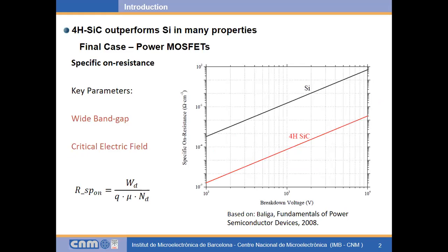Well, our final use case are power MOSFETs, silicon carbide power MOSFETs. In this way, silicon carbide outperforms silicon in most of the main properties. Here we have specific on-resistance with respect to the breakdown voltage, where we can see that silicon carbide has a gain of 3 orders of magnitude with respect to silicon. A factor 10 can be attributed to the depletion region width, and the factor 100 to the doping concentration.